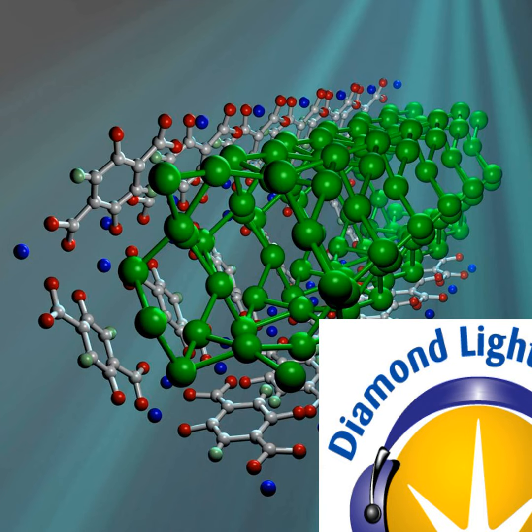While in the NOTT-300 system, because it's made in water, there isn't any amine functionalized group within the MOF host. Well, the only functional group within the host is a hydroxy group, and that was from the water and is non-toxic. And by using Diamond, we successfully identified the site of this OH group within the MOF host, and we successfully see the interaction between the adsorbed CO2 and SO2 molecule with this OH group.